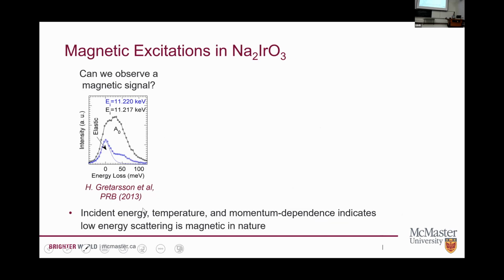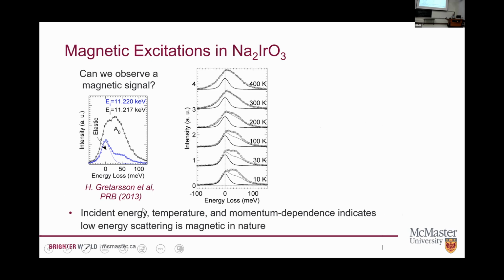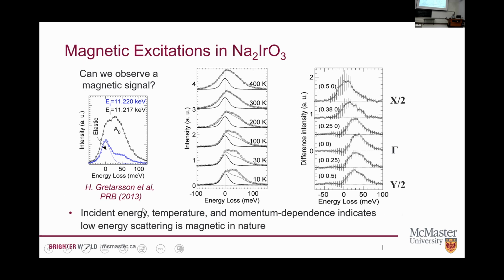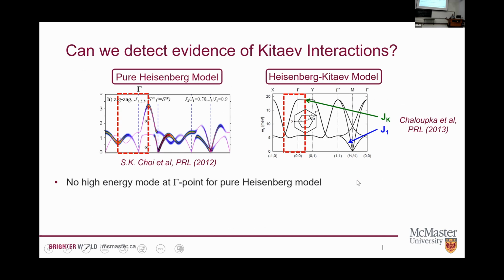So the first thing we want to see is do we see a magnetic signal? And the way we determine if a signal is magnetic is, does it have the right energy dependence? Does it resonate as we go through this absorption edge? It does. Does it have the right temperature dependence? If we warm up, our magnetic peak should go away. It does. And does it disperse at all? And again, it's a little difficult to pull this out from the background, but we do get a feature that looks like it has momentum dependence too. So we have this feature that looks magnetic.